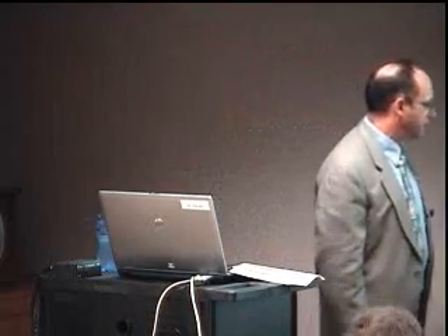We did some rebound hammer testing, which didn't tell us very much, and we did use the James R cover meter to try to see if one potential issue was that the reinforcement wasn't where it's supposed to be. Now this is probably way too small for you to see in terms of the depth. It'll be easier to see in the report.